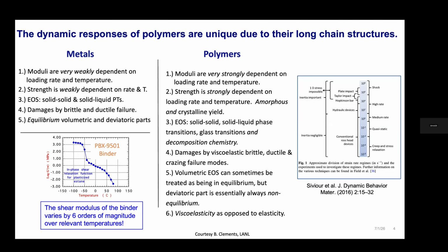So for example, the amorphous domains and crystalline domains can lead to different viscoelastic properties above and below the glass transition, and also crystalline phase transitions that are only within a portion of the polymer network. Going down to bullet number 3, within EOS, of course, you're going to have potentially solid-solid transitions associated with crystalline domains. You could have solid-liquid, or solid above TG transitions, glass transitions, but also because they're organic materials, and I'll touch on this, when you hit a certain temperature in the dynamic loading, they undergo decomposition chemistry, much like explosives.